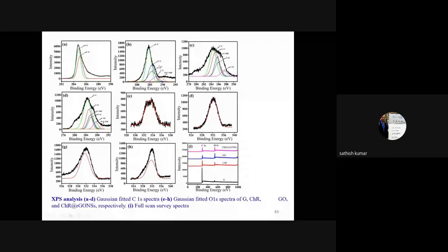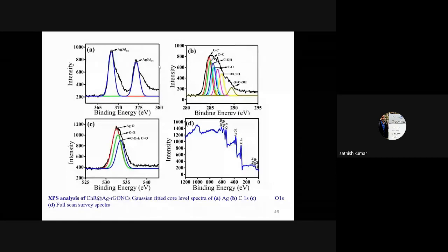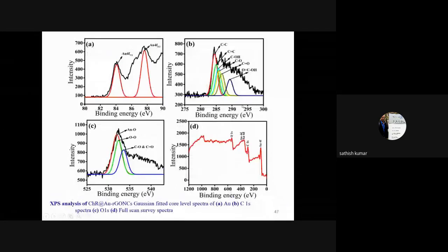In case of the composites, here we can see the core level spectrum of silver indicates the presence of silver that is being hybridized on the surface of the nanosheets, and all the functional groups due to the presence of chrysene. Similarly, for the gold nanoparticle also, the core level spectrum clearly shows the presence of gold as a major element, and other functional groups indicate the presence of chrysene.